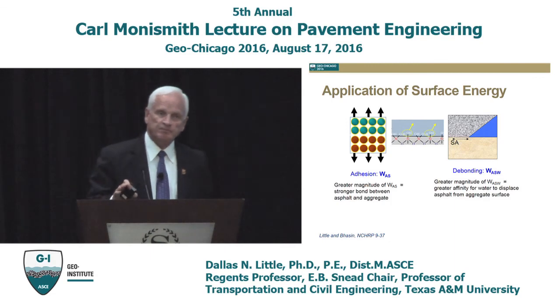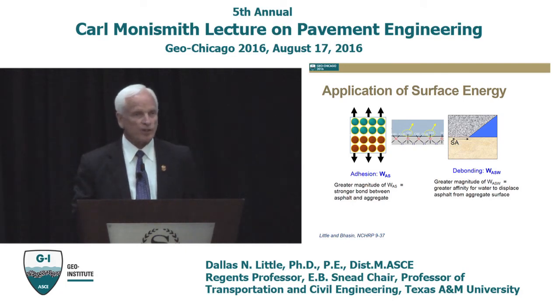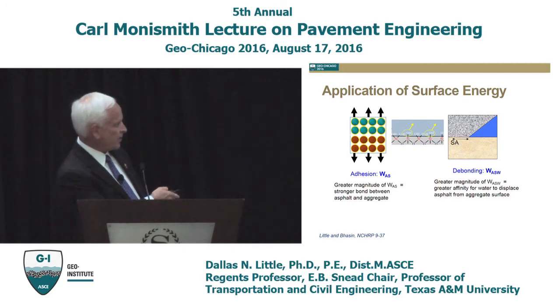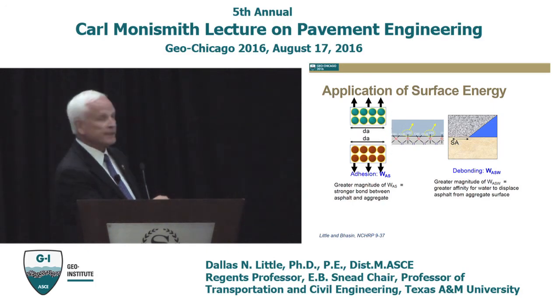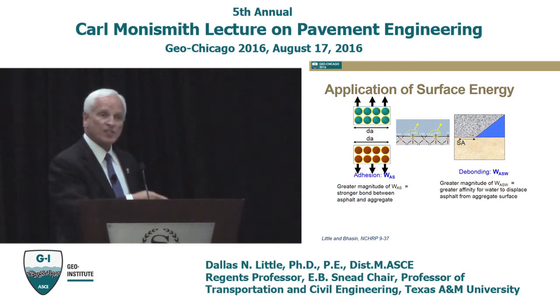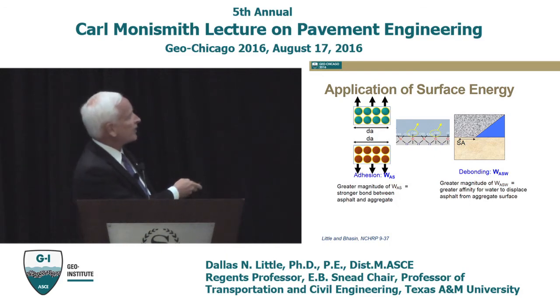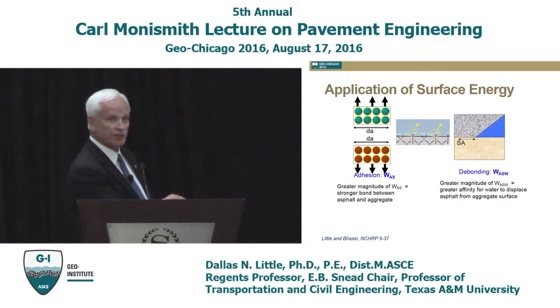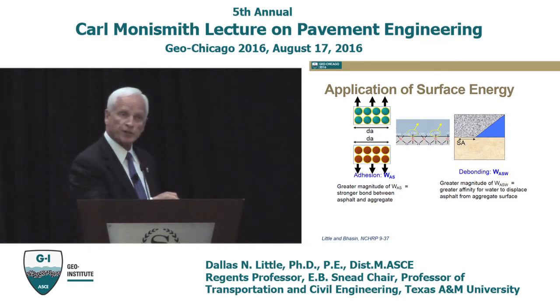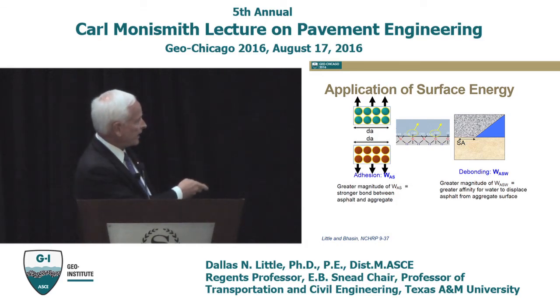We talked about some of the basic fundamentals behind adhesion. So we did a lot of work on looking at adhesion and how aggregates and asphalt bond together. So a little animation here. Let's suppose the red is an asphalt, A, and the gray here is a stone, S. So the work of adhesion between the stone and the asphalt, as I pull them apart, defines the bond strength. So if we know the surface energy of the stone, which we can measure, and we know the surface energy of the asphalt, which we can measure, we can actually calculate the adhesive bond strength.